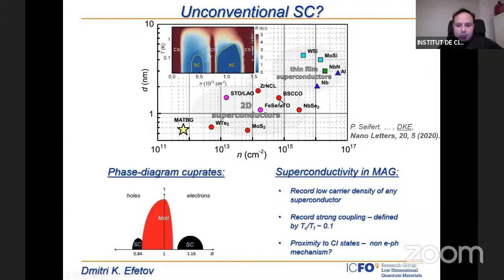So it's really an unusual superconducting system. And for this type of low carrier density, graphene also has still a relatively high TC. So right now, the record TC is around 5 Kelvin. But compared with a carrier density of only 10 to the 11 electrons per centimeter squared, this is really outrageously high TC. So currently, there is a big debate on how to interpret the superconductivity.